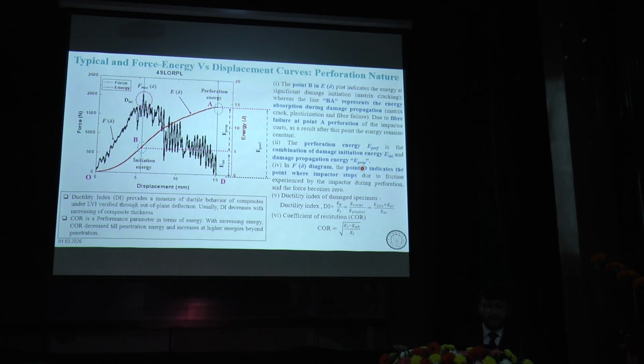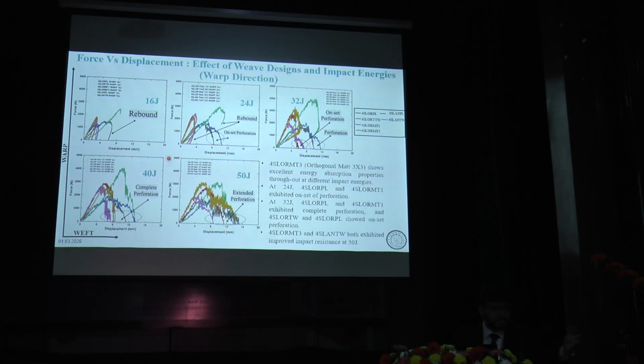As time is short, I'll go a bit quicker now. Here's another way to evaluate the force displacement curve for more data. This isn't a straightforward curve - it tells a lot of story. What is the initiation energy before the peak force is achieved during the impact event? What is the perforation energy area received after the peak force? In the force displacement curve, at 16 joules I got rebound for all structures; at 24 joules, rebound and onset perforation, which is intermediate; at 32 joules, some structures showed onset perforation and perforation. Obviously 40 and 50 joules gave complete perforation. The interesting fact is it tells me how to make a relationship among them and give a ranking, which I derived by calculating bending stiffness from this force displacement curve.